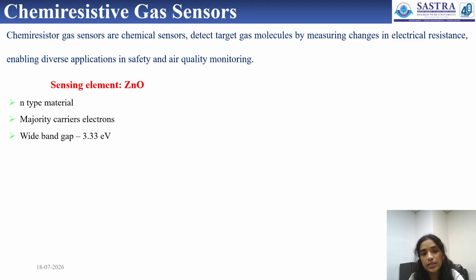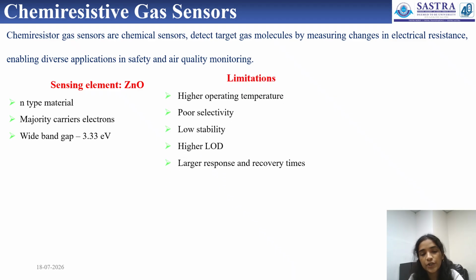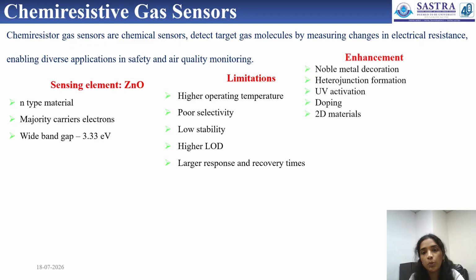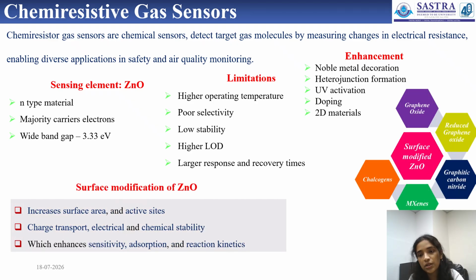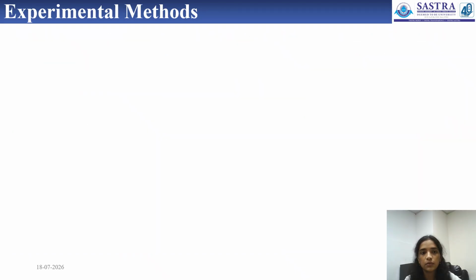And zinc oxide has certain limitations such as higher operating temperature, poor selectivity, low stability, higher limit of detection, and longer response and recovery times. These limitations have been addressed by using noble metal decoration, heterojunction formation, UV activation, doping, and addition of 2D materials. So, in this work, we are focusing on surface modification of zinc oxide using graphene oxide, reduced graphene oxide, graphitic carbon nitride, MXenes, and chalcogens. This surface modification increases surface area. It provides more active sites for gas molecular interactions, and also helps charge transport, electrical and chemical stability, which enhances sensitivity, adsorption, and reaction kinetics.